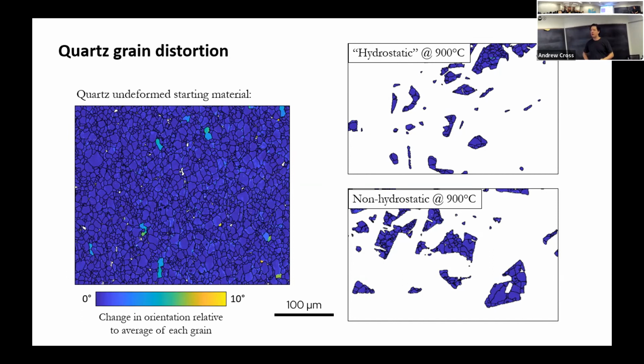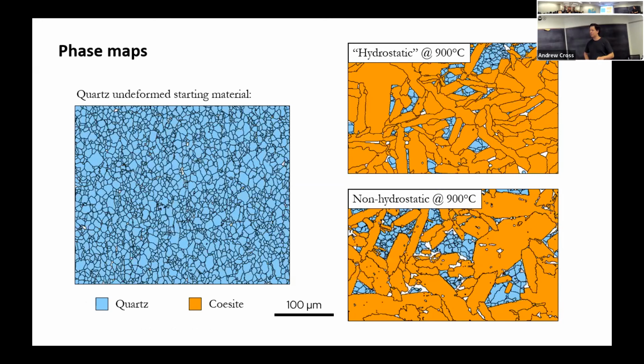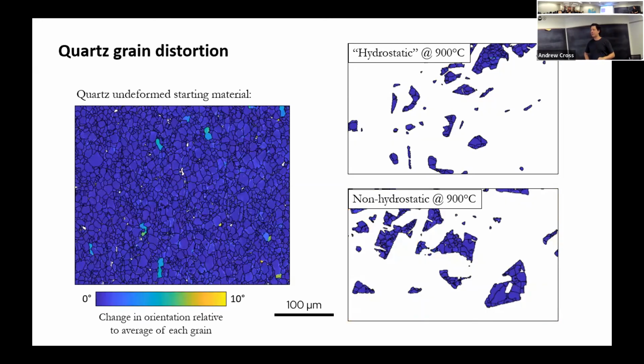So for the most part, our undeformed starting material has fairly uniform orientations within individual grains, so it's not too beaten up. If we pluck out just the quartz grains from our EBSD maps, we've got a few small areas remaining. Again, we don't really see that much internal misorientation, which is the phrase I'm going to use, referring to internal changes in orientation that indicate some sort of intragrain deformation. So in both the hydrostatic and the non-hydrostatic case, quartz isn't really doing an awful lot. It's just kind of sitting there. It's not being internally deformed, which we might expect.